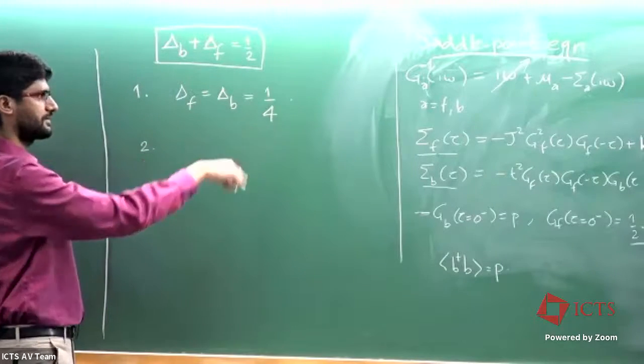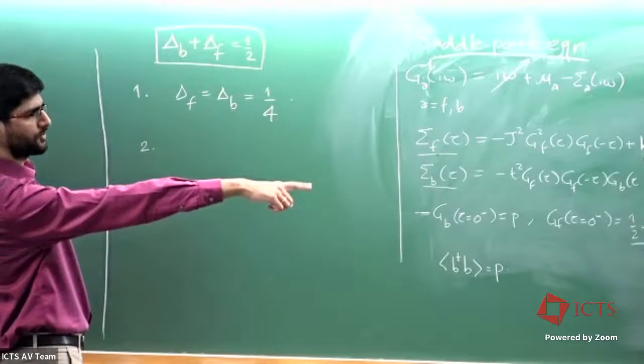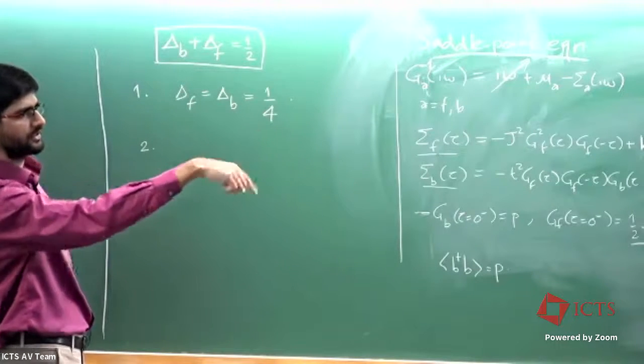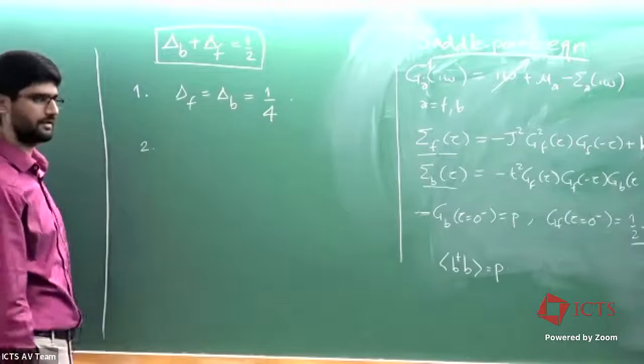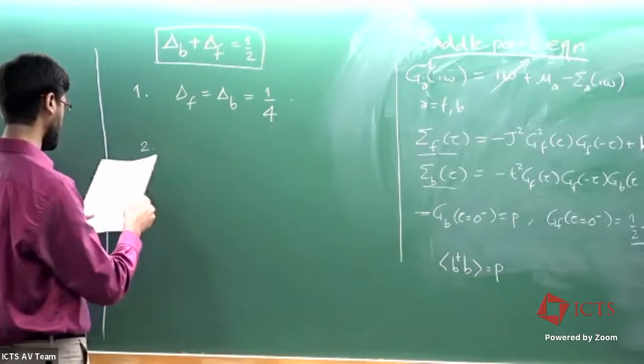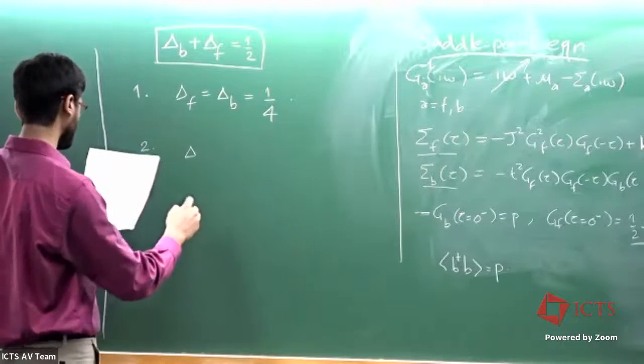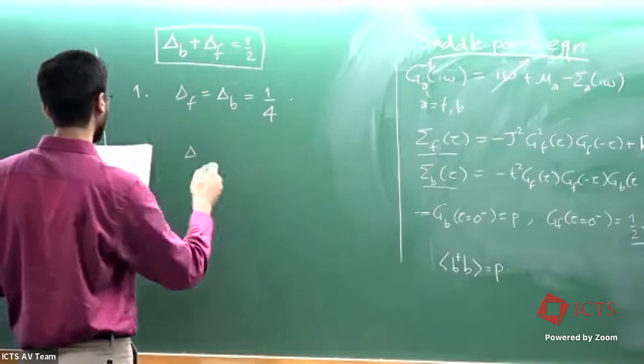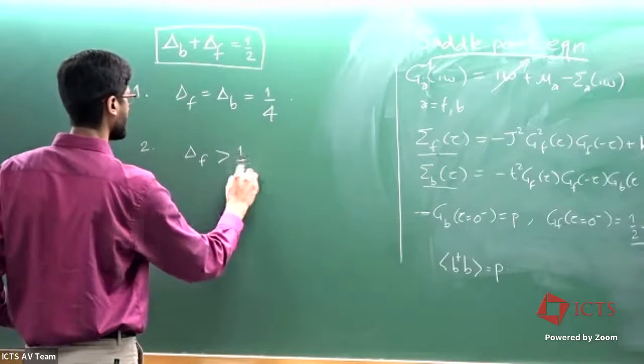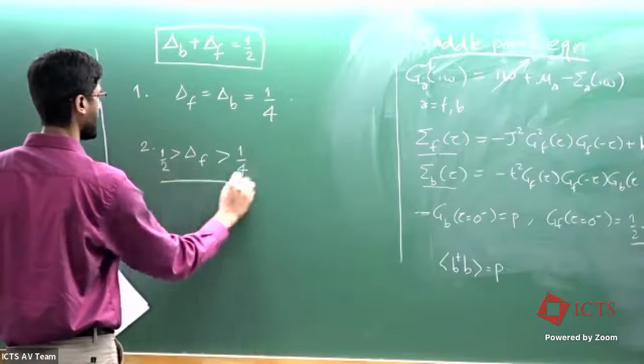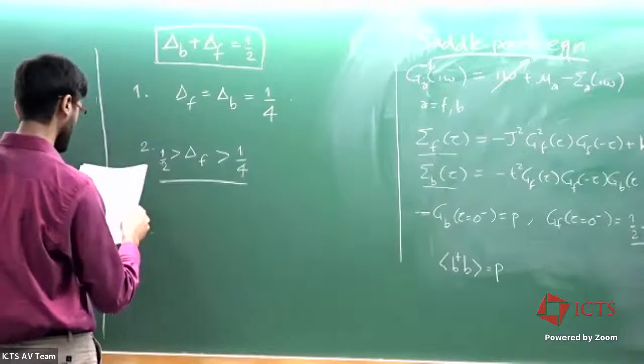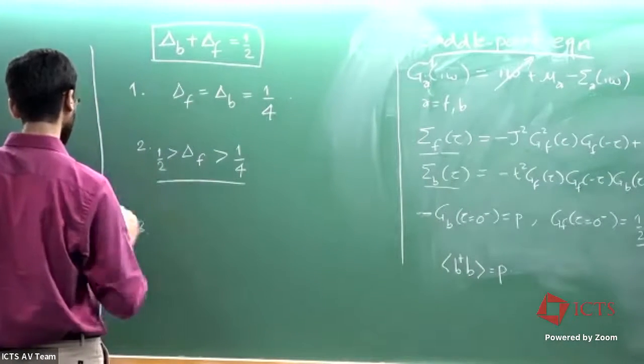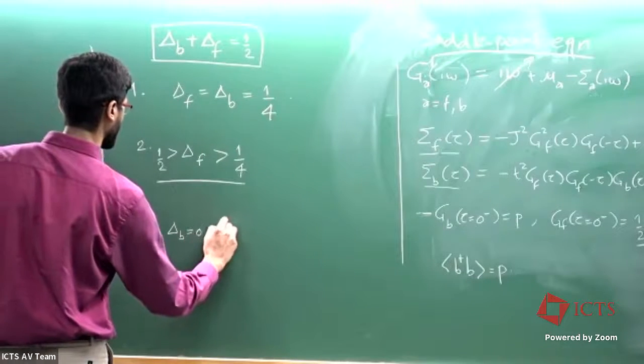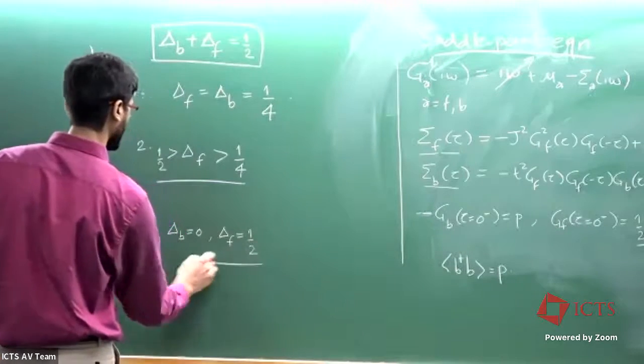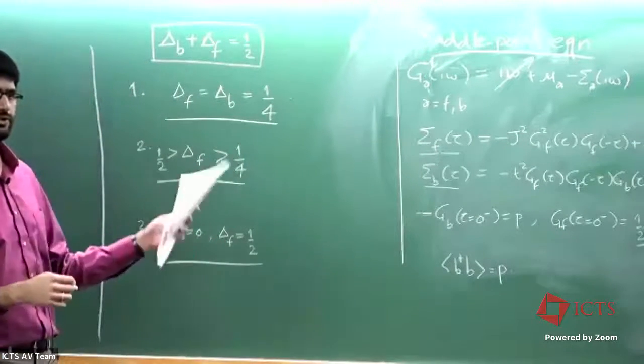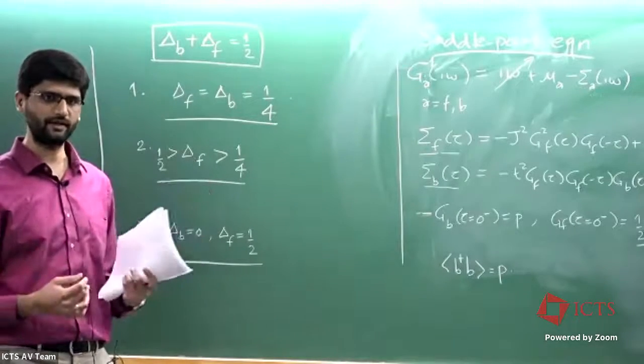One solution is delta F equals delta B equals 1/4. So you basically equate the exponent from this Schwinger-Dyson form to the J² term. So that gives you this solution, that these have to be equal. And then the other solution is if you equate it to the other one, then depending on that the first term dominates, you get the other solution, which is delta F greater than 1/4, but of course it has to be less than 1/2. And of course the third solution is the limiting one, where you have delta B to be 0 and delta F is 1/2. So these are the 3 solutions of this random t-J model that I have been talking about.